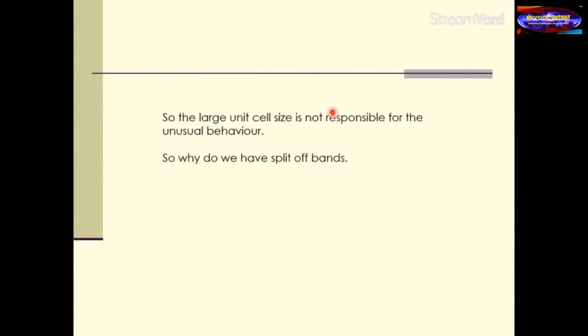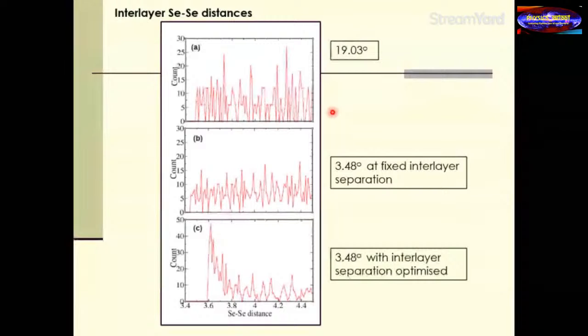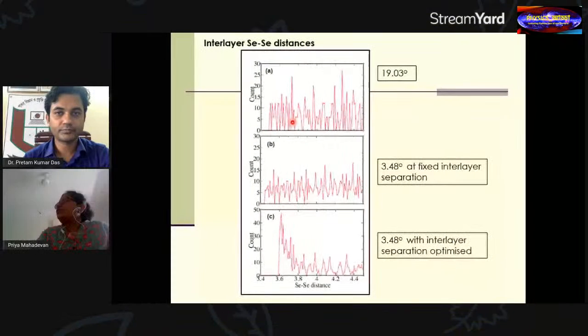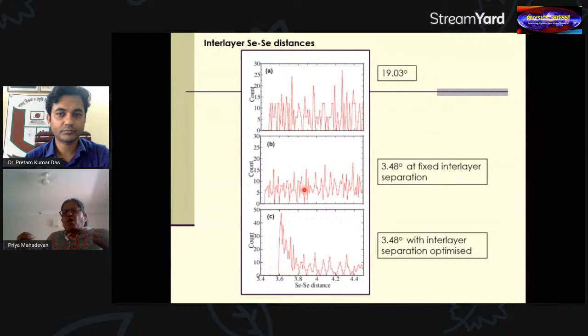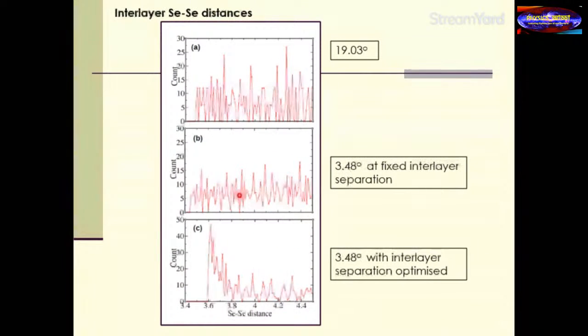And as I said, I was talking about what actually controls this, which controls these interactions, and I showed you a picture. It's actually this hopping between the atoms of the two layers that controls the electronic structure when I have the additional layer. But you can see that at least these two have very similar interlayer distances, because the hopping interaction, you can understand this even qualitatively, in the tight binding model has these hopping matrix elements, and it depends on the separation between the two atoms. If they're closer, obviously the tendency to hop should be larger.